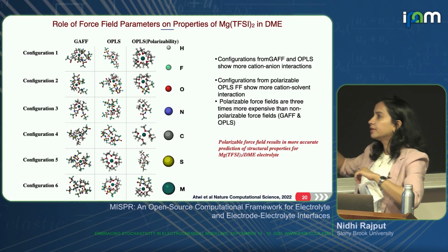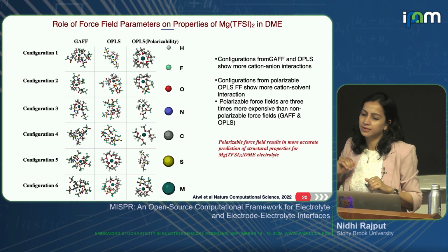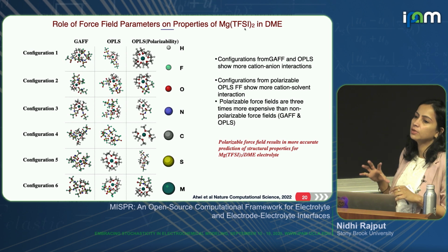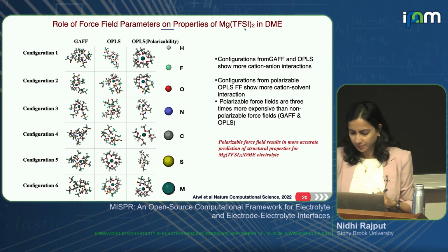So based on the experimental results in our work and the previously reported experimental data, our conclusion was that for this particular electrolyte, the polarizable OPLS force field gives the most accurate structural properties.